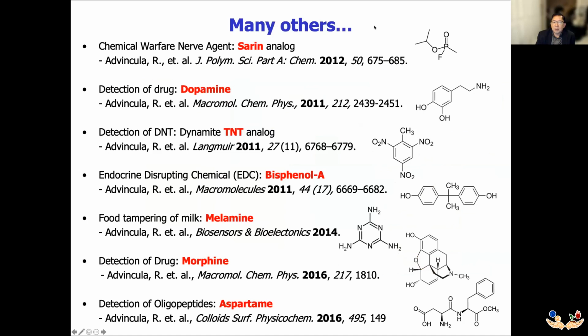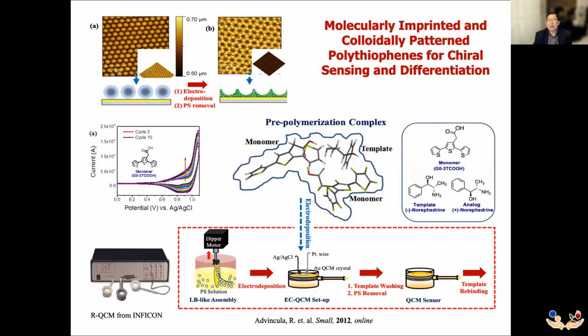polymerizable molecularly imprinted polymers. And we have been busy trying to demonstrate it on various types of analytes, ranging from organophosphate or sarin analogs or dopamine, bisphenol A, melamine, morphine, aspartame, and we've seen this demonstrated even on oligopeptides associated with the dengue virus. As you can see here, we can combine this with colloidal nanosphere lithography and the molecular imprinted approach to produce high surface-to-volume surfaces that are capable of sensing or being templated to make sensing. So in this case, we again have this monomer templating here, a norephedrine enantiomer.